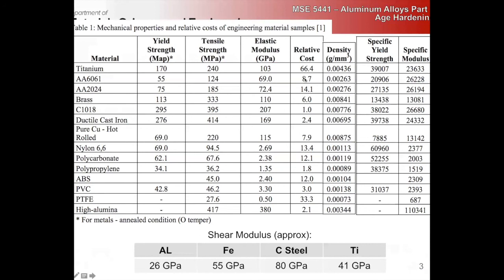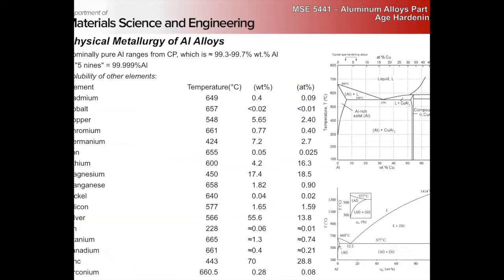The big issue, right, if we look at the relative cost with respect to steel, depending on the alloy, 9 to 15 times the cost of steel, right? But not nearly as bad as titanium, right? 66 times, right? That's the big driving force for more and more aluminum use, this high specific strength and low density, right?